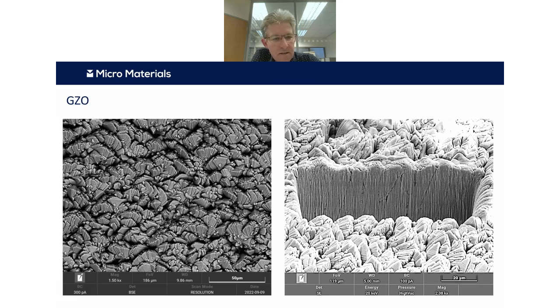On the gadolinium zirconate, essentially you've got a slightly similar scallop-shell type structure, if you like, and again it's columnar. What I've done on the right is try to white out that image a bit to emphasize some of the columnar structure. You can maybe just make out the slight orientation: on the 7YSZ, the columns were oriented normal to the surface. Here they seem to be angled about 15 degrees away from the surface. So that's a slight difference between these two materials, and that will have an impact both on its thermal conductivity, but also potentially on its impact resistance.